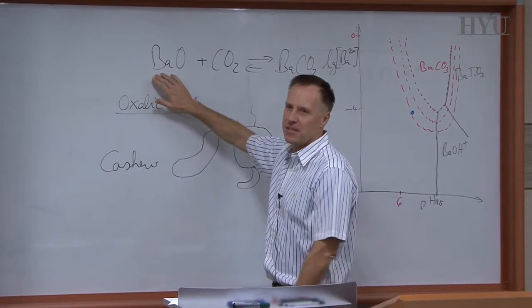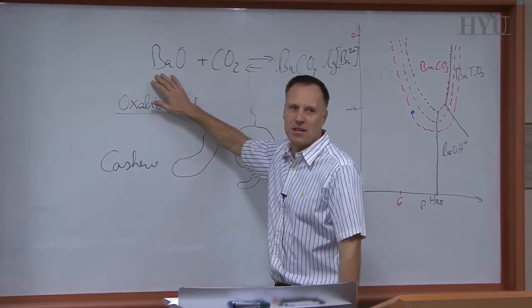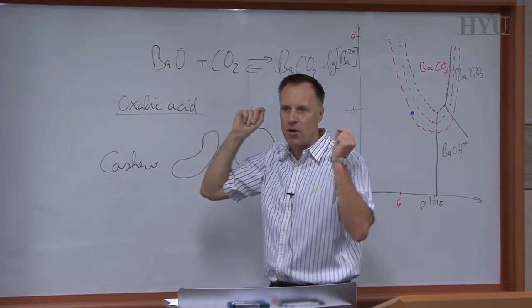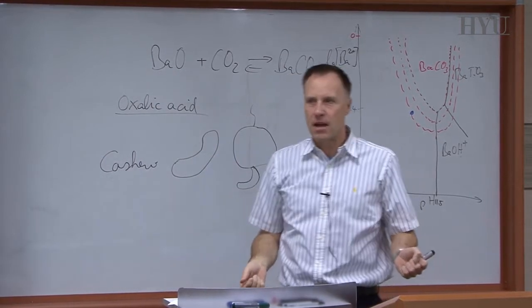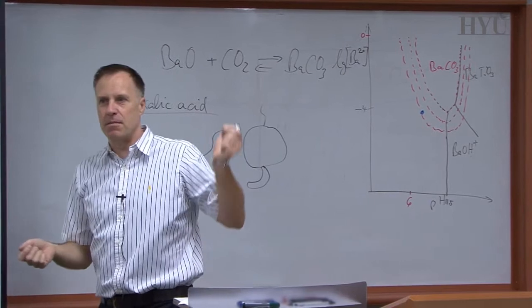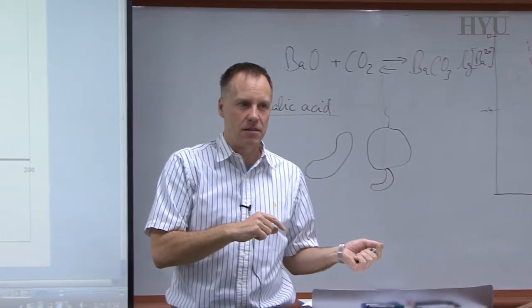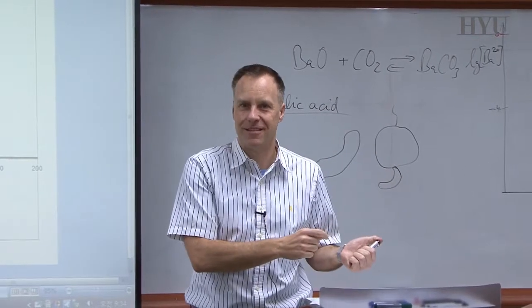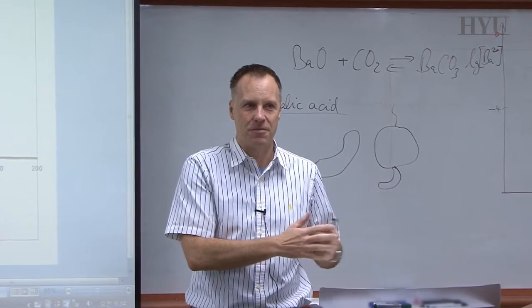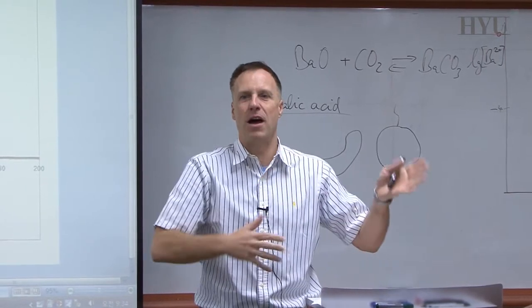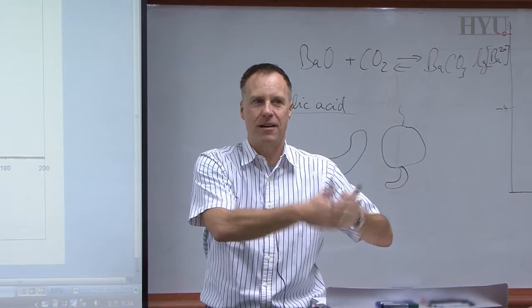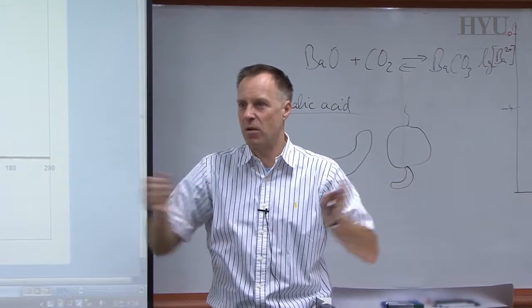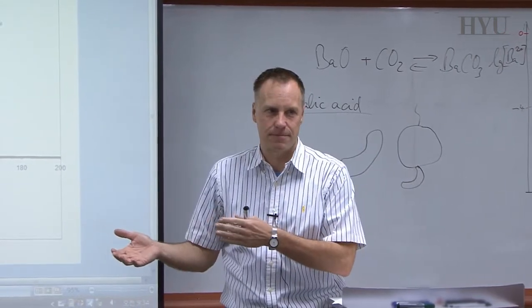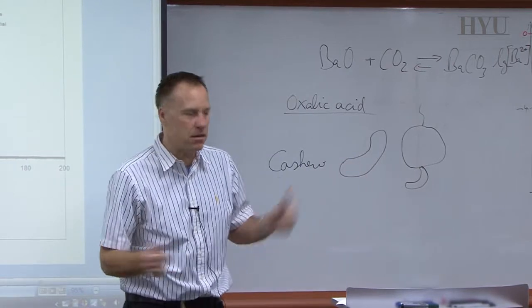Obviously, barium, similar group, also reacts really well with that and forms a very insoluble compound. Actually, it's so insoluble that the manufacturers for barium titanate work with oxalic acid. They have basically solutions of barium and precipitate them with oxalic acid and then react it with titanate. This is one of the routes to make barium titanate particles. And so we can use this here again.